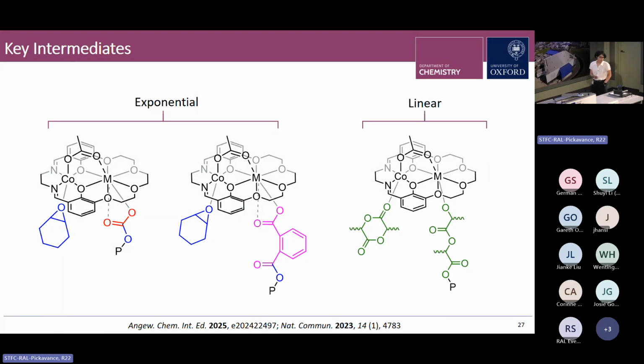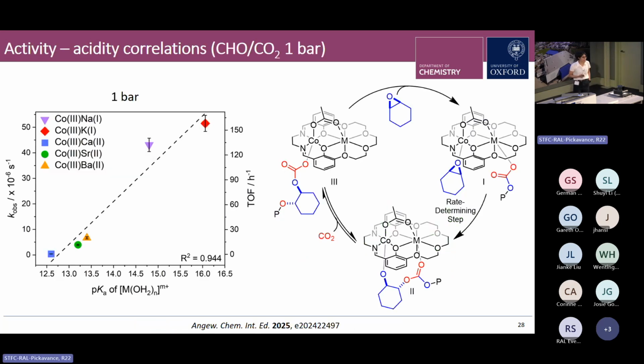But in the case of the ring opening polymerization of lactide, the key rate determining intermediate is an alkoxide, where the nucleophile could only bind to the S-block metal in a monodentate coordination mode. Potentially that gives rise to a more stepwise increase in catalytic activity with decreasing S-block metal Lewis acidity, and therefore the correlation is linear. So perhaps we can use this idea to rationalize why we see a linear activity-acidity correlation for the copolymerization of CHO and CO2 at reduced CO2 pressure.